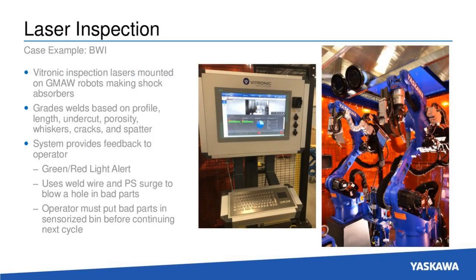So here's a case study with laser inspection to give you an example. This was working with BWI, who's a strut manufacturer, shock manufacturer, and they chose a Vitronic brand laser. Now these lasers are mounted on the robot arm with the torch and the rest of the arc equipment. They grade each of these welds with these lasers after the weld is complete, but before the weld's even done, it verifies that the part's in place and that it's the correct part.